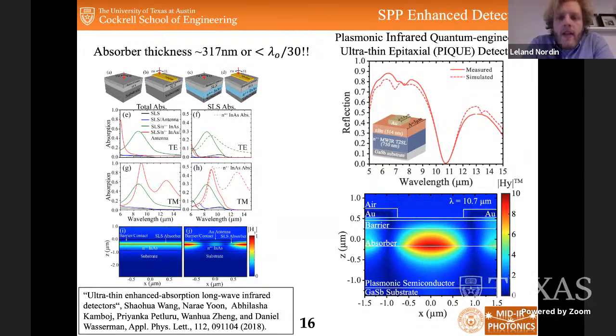And then shown on the right is the actual measured reflectance from these detectors with these gradient couplers patterned on top. We ended up using patch antennas, so we didn't have any polarization selectivity. And then also simulated results using rigorous coupled wave analysis. This is another simulation package from our collaborators at UMass Lowell, Victor Podolsky's group, and you see a very good match between our experiment and simulation, and then a rather significant dip in reflectance around 10.7 microns, suggesting coupling to some sort of mode. If we then use that same software package to calculate the fields, you can see a rather bound mode at the plasmonic semiconductor absorber interface, suggesting that we are coupling to some sort of SPP.